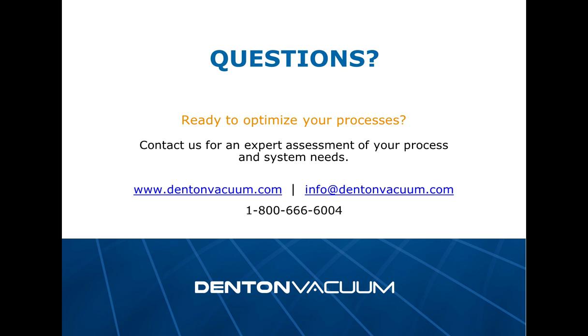Do the high-stress coating methods deform the base material? And if so, what is done to compensate for the deformation? So stress control is a very challenging topic. For high numbers of layer stacks, it has to do with the stack design. There are possibilities of controlling stress with deposition on the opposite side of the substrate to reduce the overall stress level. But with some deposition technologies, like IBS, ion beam deposition, you would have more stressed films in the end. But also, again, film design or stack design in this case would play a significant role.